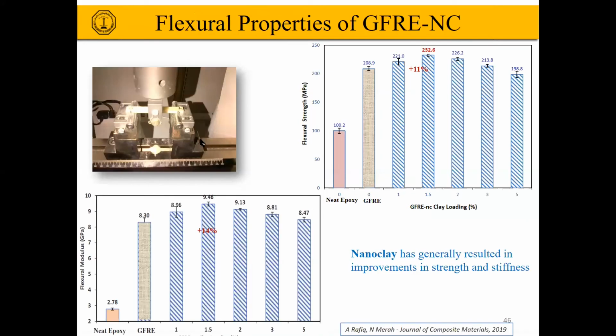And we looked at the flexural strength of the glass fiber and how it is affected by the addition of nanoclay. This is the epoxy. This is the glass fiber reinforced without nanoclay. This is the glass fiber reinforced with nanoclay, which we call the hybrid nanocomposite. You can see that after adding 1.5% of nanoclay, we increased the strength of the glass fiber epoxy by 11%. Going to 2%, we still have like 8%.